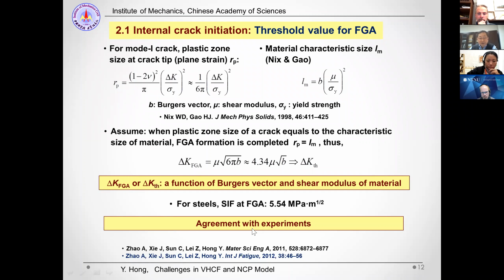This value is just in relation to shear modulus and Burgers vector of the material. So it's very interesting and important, showing that delta K FGA or delta K TH is a function of Burgers vector and shear modulus of the material. For steel, this value can be calculated as about 5.5 megapascal root meter, and this is in agreement with experiment.